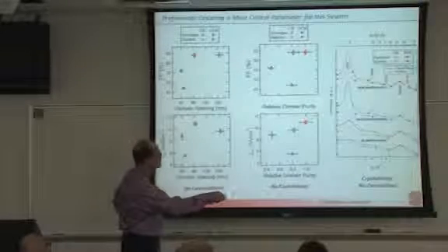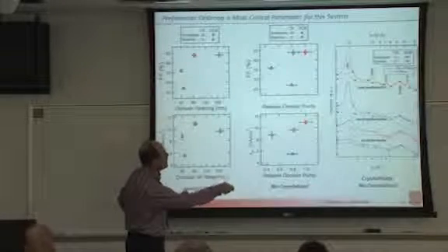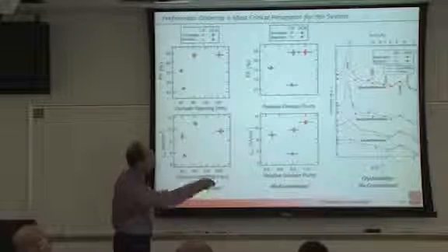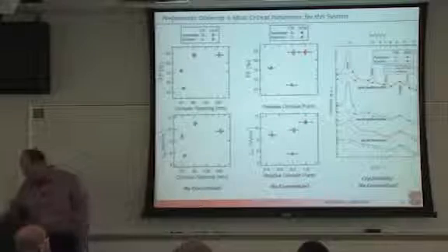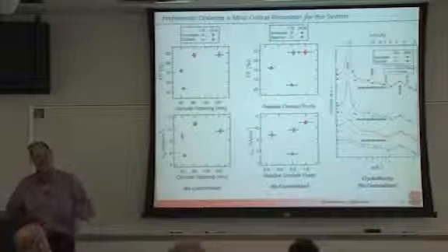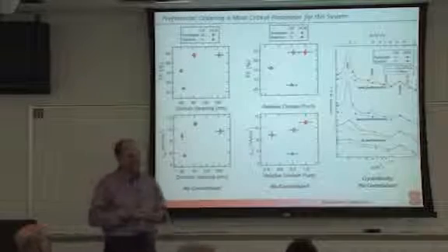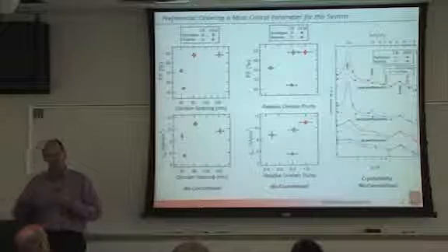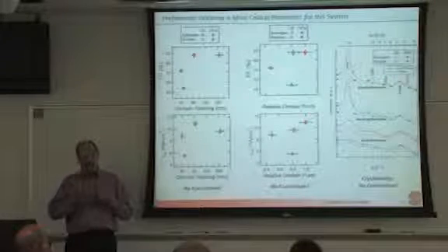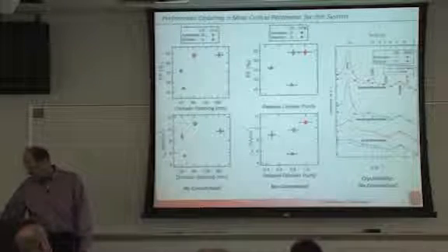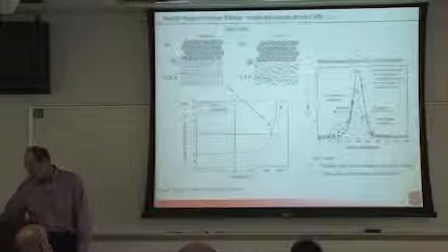If I look at the pi-pi correlation, I get maybe a little bit better relationship, but no matter what we analyze, there's no good correlation to the crystallization. So it looks as if in this particular material system, what really matters is this molecular orientation correlation relative to an internal three-dimensional interface, and that's the bulk heterojunction interface.